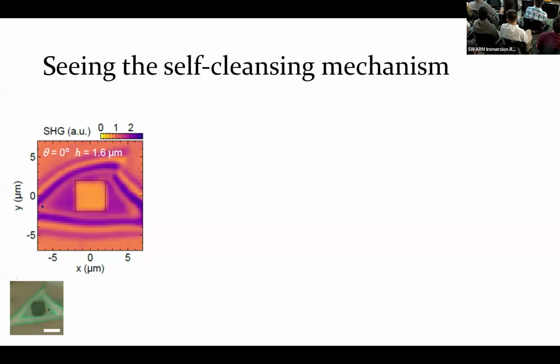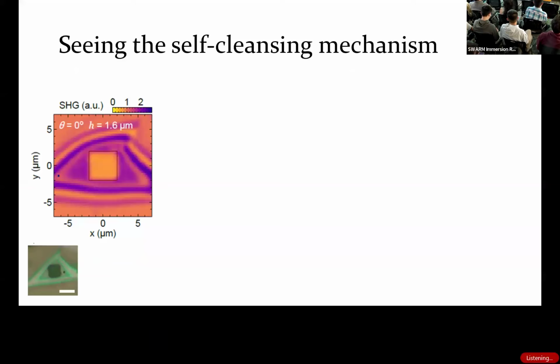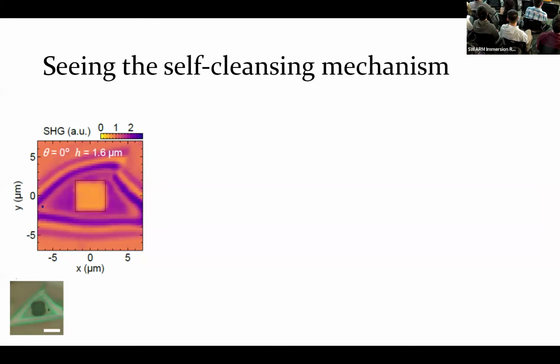Now, in order to see that, we can also look at this map of the second harmonic generation. So the square in the middle is basically the size of the silicon pyramid where we put down the 2D material. It is showing you a map of the second harmonic generation. We can scan the laser across the sample and see which point generates second harmonic generation stronger or weaker. And the lower left shows the corresponding optical image of the device.